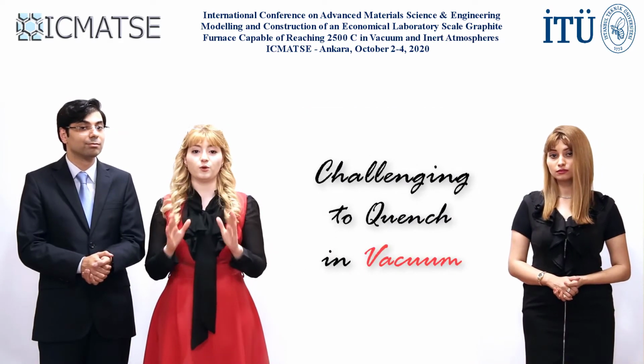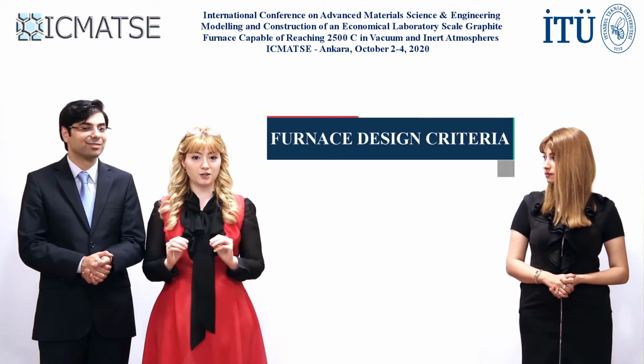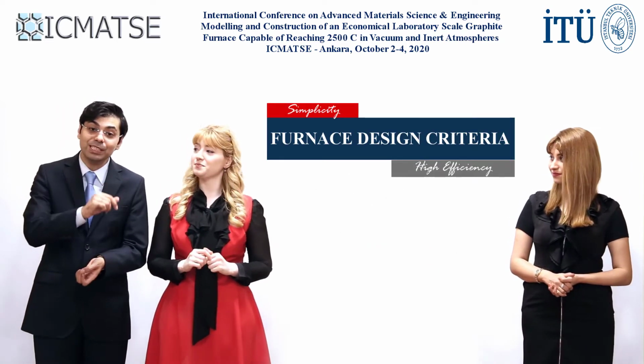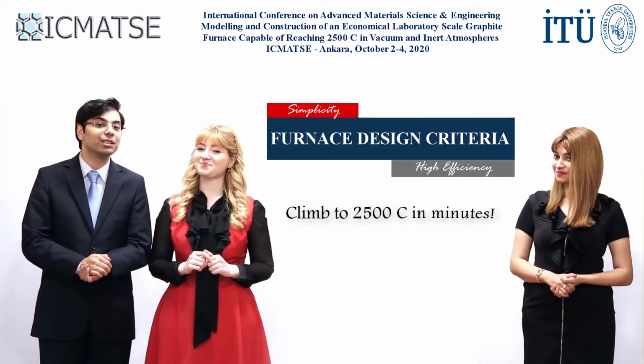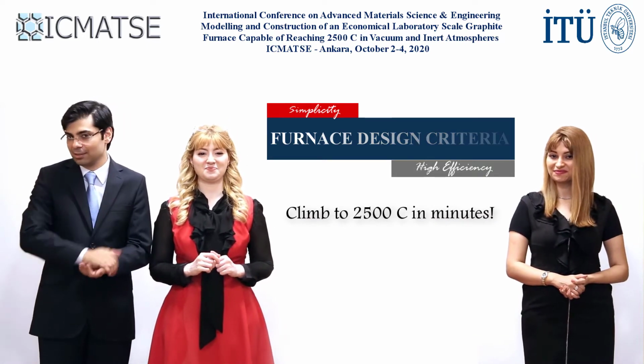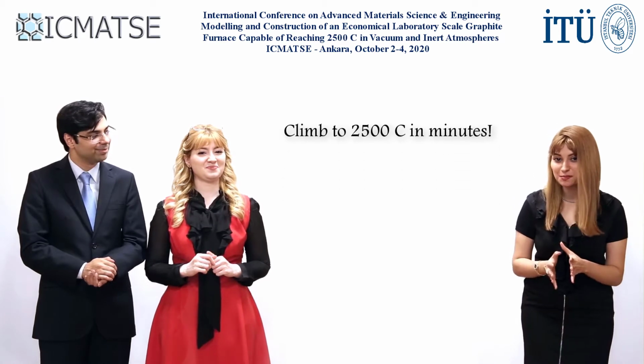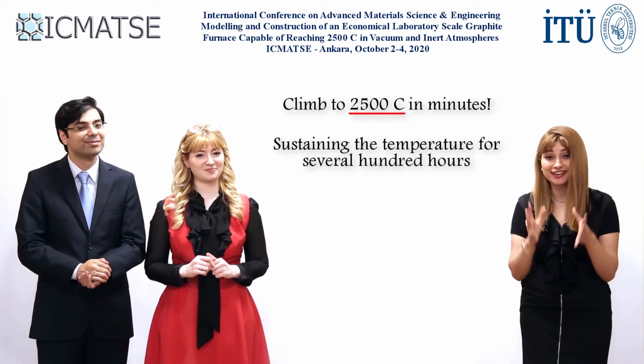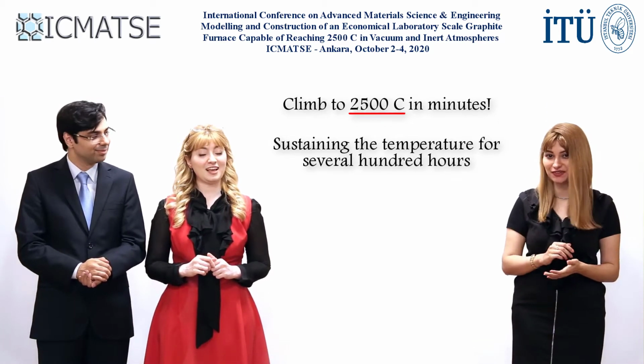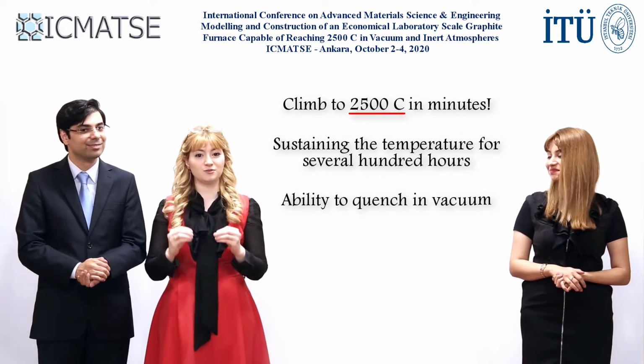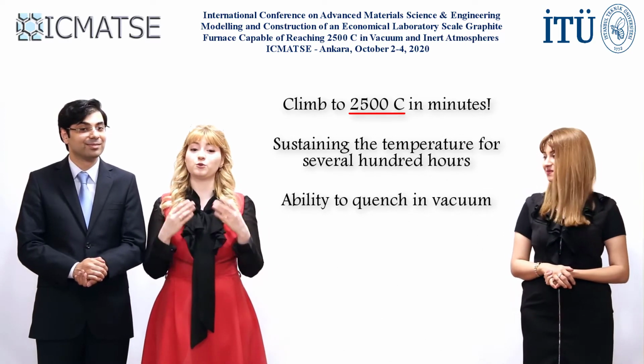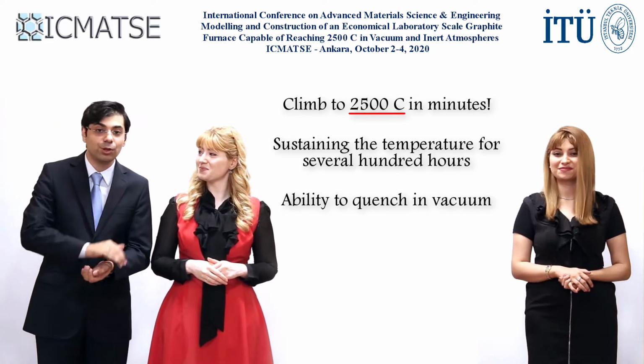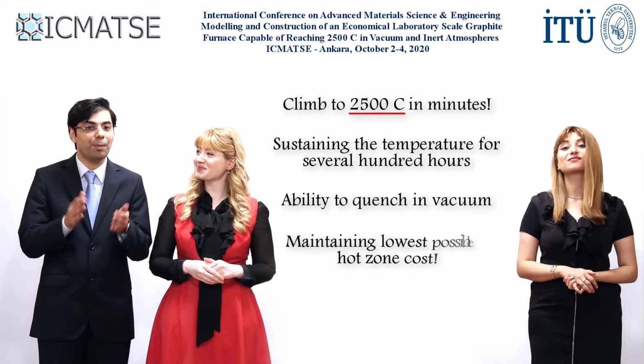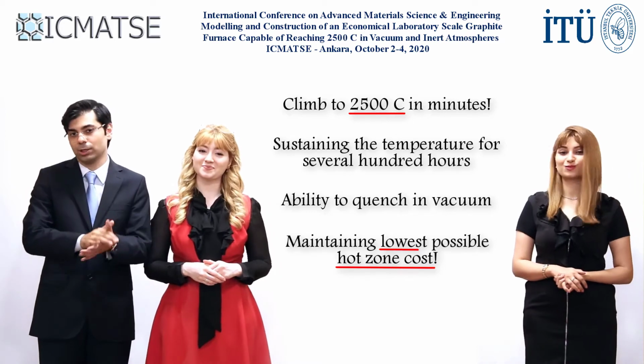So with these points in mind, we proceeded with the following design criteria for the furnace. The ability to reach 2500 degrees Celsius in just minutes. Capacity to sustain the mentioned temperature for several hundred hours if necessary. The ability to cool down the furnace at very high rates without using any fluids for quenching purposes. And most importantly, maintaining the cost of the main hot zone as low as possible.